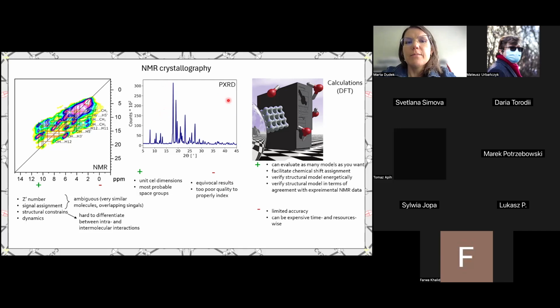And more often than not, we are also using powder X-ray diffraction crystallography, because NMR is a very local technique, so it does not give us much information about long range order, and for that we need some diffraction-based technique.